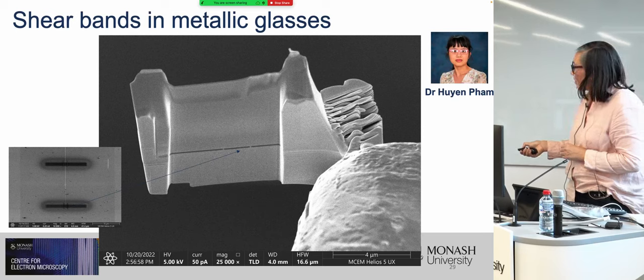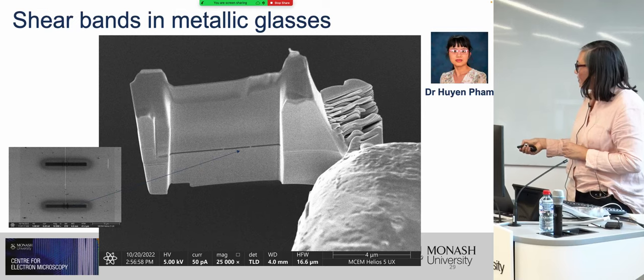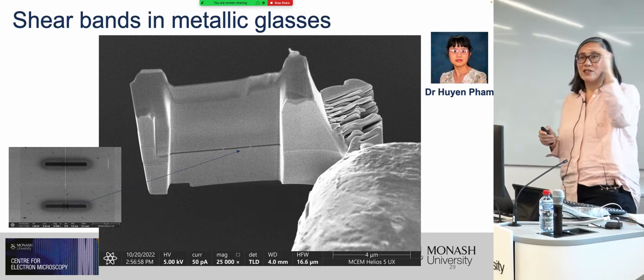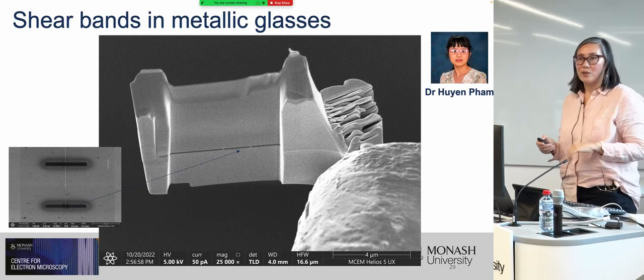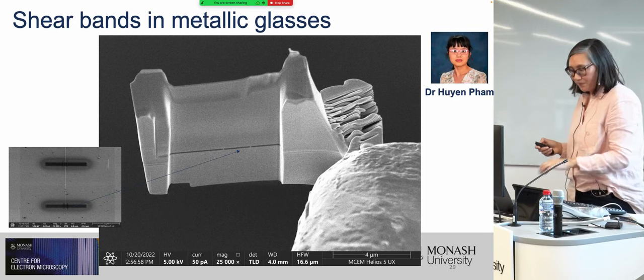We've prepared these areas to lift out in the cross-sectional configuration, so we have these two fiducial markers here. And here is this particular area lifted out here, where you can see the fiducial markers, and you can just make out the tiny, tiny shear step in the surface that marks out the shear band.